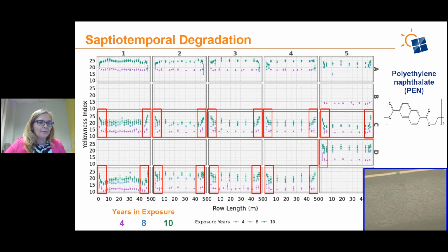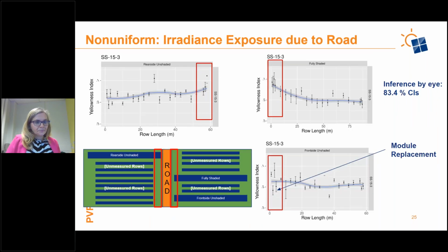What you see here on this top subrow is that it actually started in year 10, tailing downwards at the edges. What we actually identified is they started photo bleaching instead of yellowing. Also on this top row, we started seeing micro cracks in that polymer. And they had started transitioning from yellowing and forming chromophores to actually photo bleaching and having micro cracks. So we had a transition in phase of degradation types, leading towards failure.